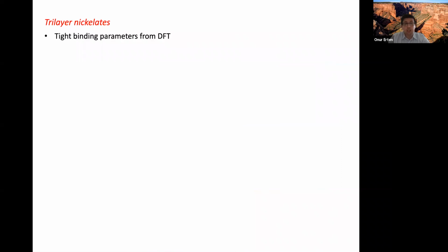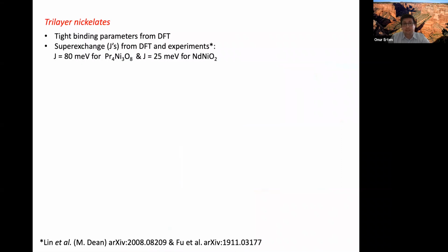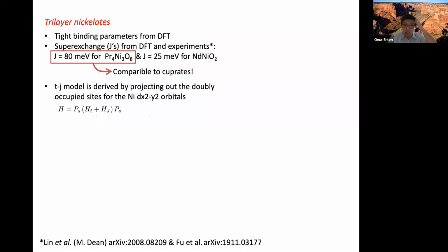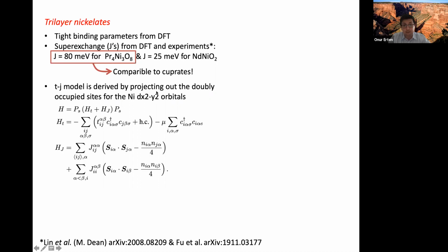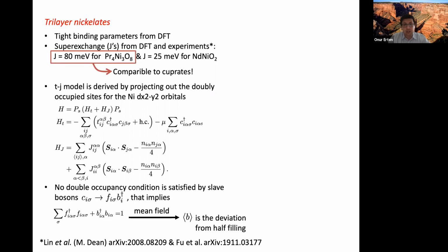And in our modeling, we take the tight binding parameters from DFT, the super exchange parameters from both DFT and experiments. And here for the tri-layers, note that the super exchange value is actually quite large. It is in some sense comparable to cuprates. And we derive a TJ model, which is pretty standard in this field, by projecting out the doubly occupied sites in the strongly interacting band. Not going to go into details of these. Happy to discuss further later. And we do a slave boson mean field theory to solve for superconductivity. And again, these are pretty standard in this field.